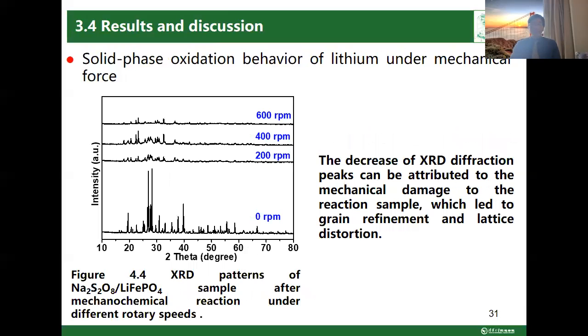The result of the figure also shows that the XRD characteristic diffraction peak of the material decreases with the increase of the rotary speed. The peak position of the diffraction peak changed significantly. This indicates that under the action of mechanical force, these two chemicals underwent a mechanochemical reaction, resulting in a new crystalline phase. The decrease of the XRD diffraction peak can be attributed to the mechanical damage to the reaction sample, which led to grain refinement and lattice distortion.